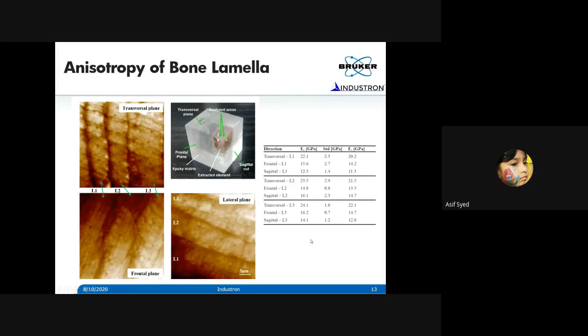Here I'm giving in the tabular column what the modulus values are. In the transversal plane, the modulus is much higher, about 22 GPa. In the frontal plane it is about 15.6 GPa. In the lateral plane, it's about 12.5 GPa. And this is for 3 different lamellae. They are pretty close, but you can see from this experiment that the transversal plane has the highest modulus, which means that in that direction, it has the highest load carrying capacity elastically without undergoing any permanent deformation.